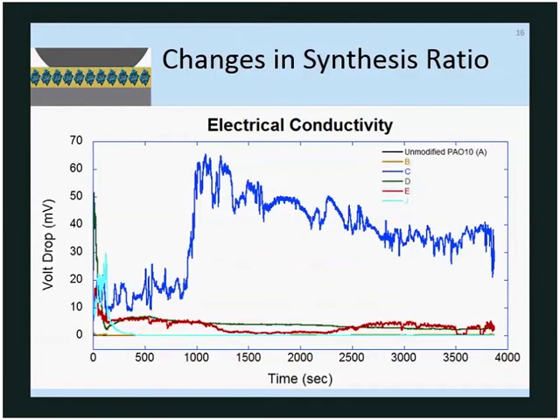And then electrical conductivity. This ratio E is the one that works for a lower friction coefficient, and that also is seen here with a value of electrical conductivity above 0 in the beginning, and then it drops down to about 0, and then in the end it also rises again above 0. So that indicates a possible tribochemical film layer forming.